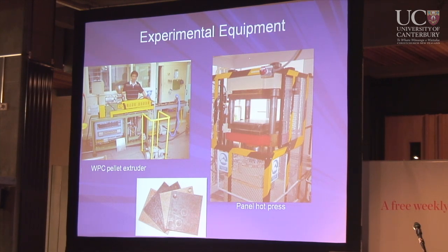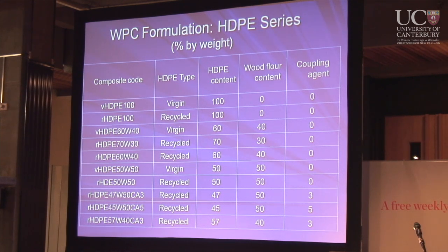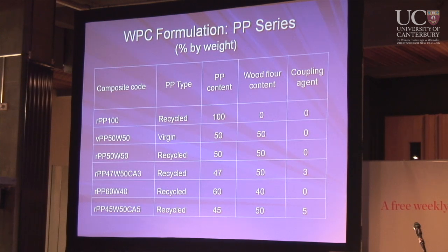So you have seen that. And we developed formulations. You can see here we use different proportions of plastic, different proportions of wood, and a very small proportion of coupling agent. This is a little bit of a secret, what the coupling agent is that holds them together. However, if you want to build a plant, I can tell you the secrets and formula. If you see a V here, it is virgin plastic; if you see an R, it is recycled, with different proportions of wood and plastic. Then we can see what the result is. And we did the same for PP, polypropylene.